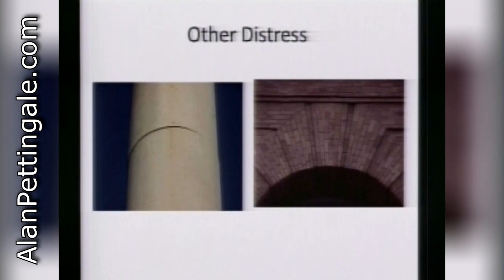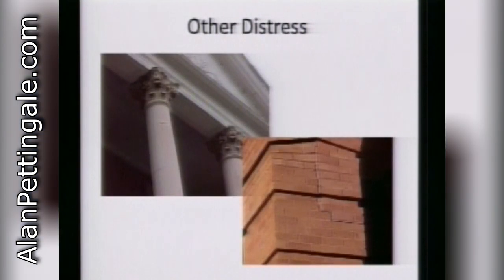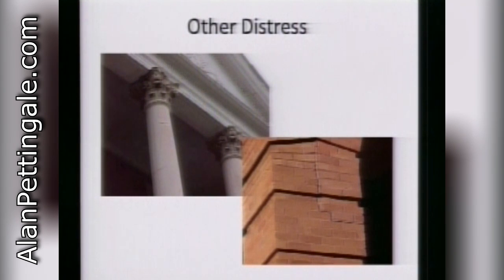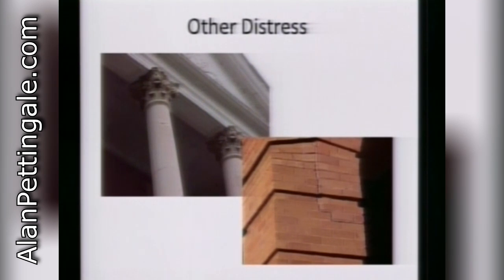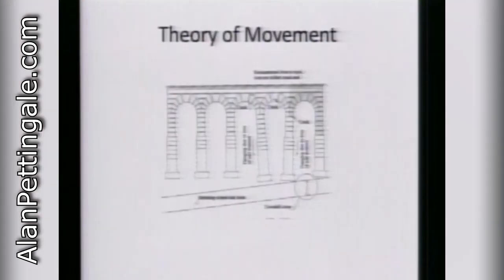There was other distress as well: the segments of the load-bearing column itself were shifting. Some brick units fell from the arch. The top of the cast stone column was sliding about an inch. You can see the joint where all the new construction meets all the existing masonry — you can not only see the difference in materials, but also see how a crack is forming. The new element is much more rigid because it's concrete.